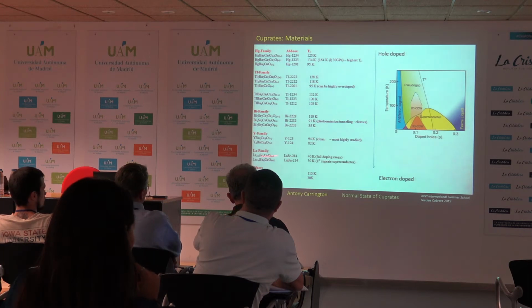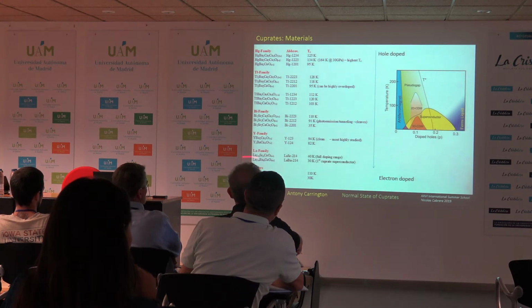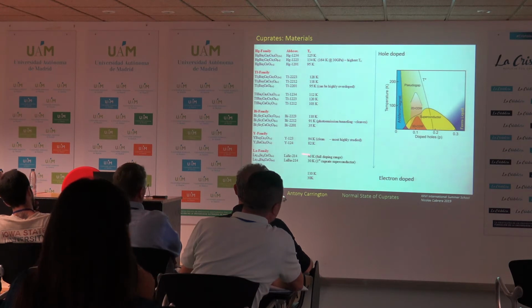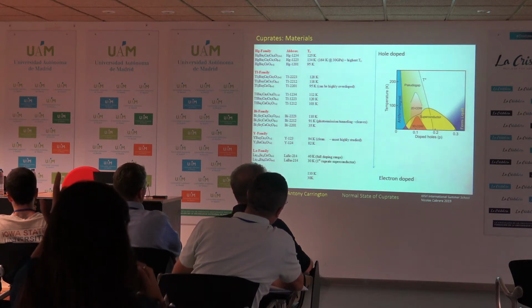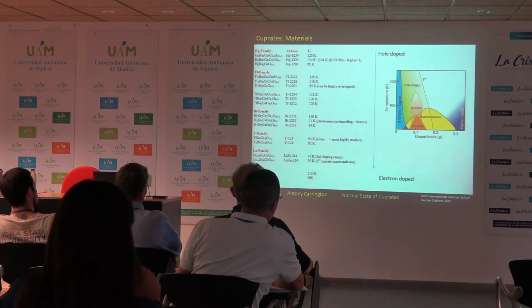In principle, this one is perhaps one of the simplest. This is one of the first ones they discovered, lanthanum strontium copper oxide. This is a single layer, and it can be doped over the full range. The only problem is it's not a high Tc superconductor. It's only got a Tc of about 40 Kelvin, and probably that's due to either strain in the lattice or disorder. Okay, so that's your orientation.